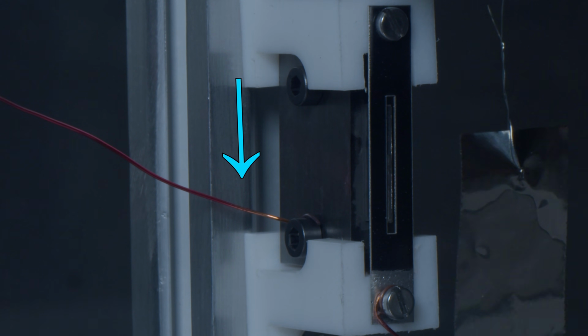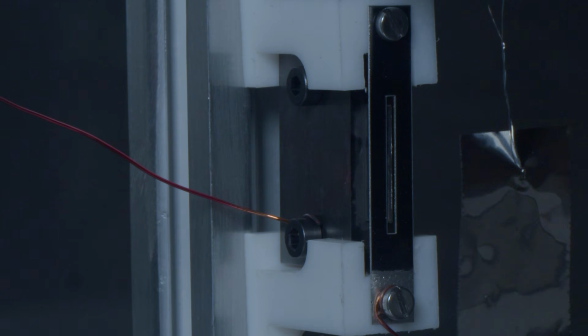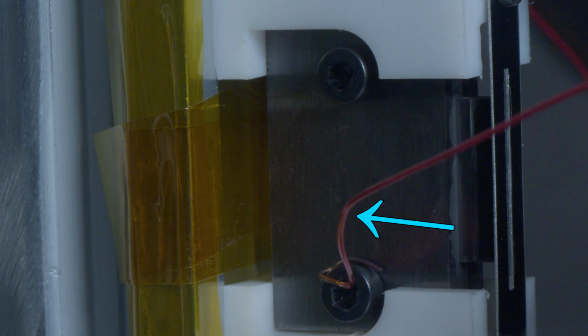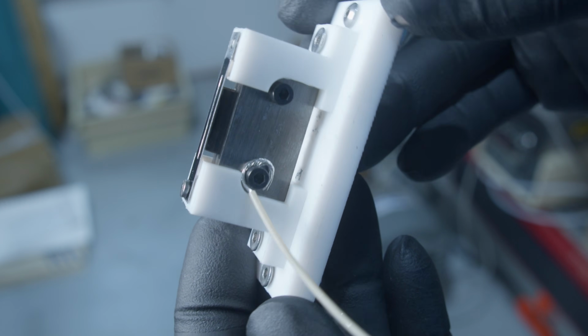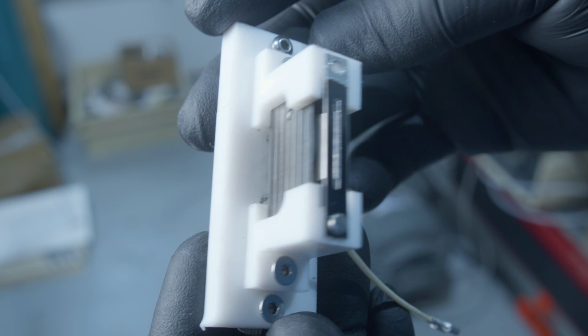There was arcing between the aluminum test stand and the wire. I fixed that with some Kapton tape and better spacing, but then there was arcing between the thruster back and the Kapton tape. At one point, the insulation on one of the magnet wires just totally came off. I don't know how well this shows up on camera, but the insulation on the wire started to arc inside the vacuum chamber, and I realized the vacuum pressure had dropped 2 orders of magnitude. So I machined a full PTFE backplate and swapped the wires over to PEEK insulation.